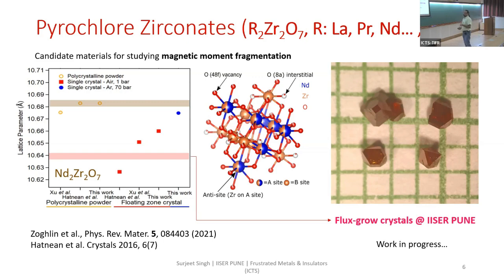So we thought we will grow these crystals by flux method, because the advantage of the flux method is that you can work at much lower temperatures compared to the melting temperature of the material. And we would crystallize directly the pyrochlore phase, not the defect fluorite phase, which you invariably get when you use a float zone technique, when you're growing directly from the stoichiometric melt. So we could get some crystals, but the lattice parameters are still not up to the mark. So this is a work in progress.